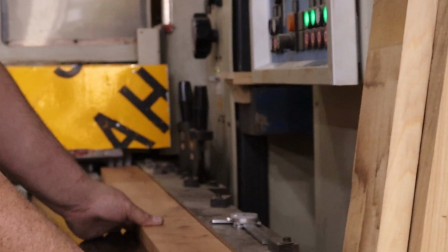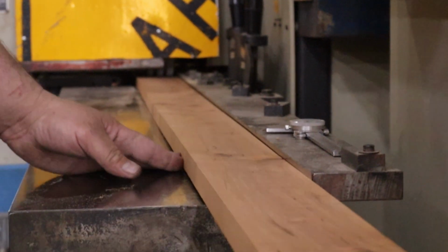And by using a vacuum kiln, this kiln doesn't case harden the wood, which means dries on the outside and keeps moisture trapped in the center. That's a case hardening. If we can eliminate that through our vacuum drying process, the lumber relaxes so you don't have stress on the material. The lumber is then, when we rip and straight line rip this lumber, we don't get pinching and splitting as we rip our material because of our vacuum drying process.